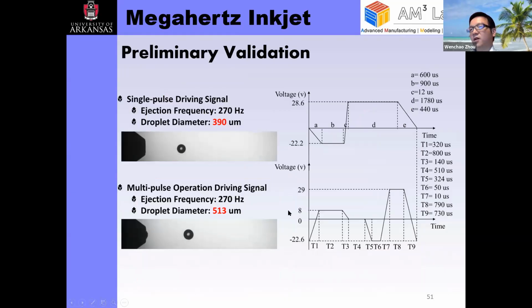So we did some experiments with a single pulse and multi-pulse. This is a single pulse, this is a multi-pulse with the signals corresponding here. And they are printing at the same frequency, but with multi-pulse, we're able to generate a much larger droplet size. It was 513 micron compared to 390 micron here. So there's still more work that needs to be done.